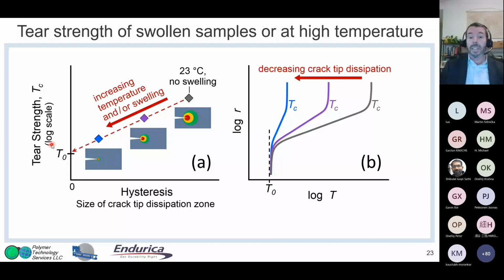So really what's going on here? Well, the fatigue threshold is not very temperature dependent, so it stays fixed. The tear strength, on the other hand, goes down as you increase temperature or you swell the elastomer. So what you're really doing is you're causing the crack growth curve to become compressed, and eventually, if you got rid of all of the dissipation, the tear strength of the material would equal the intrinsic strength or fatigue limit of the material. So that's one way. So you could measure tear strength using trouser or planar tension, measure at room temperature, maybe 80 C, 120 C, for example, and you could then extrapolate to some T0.